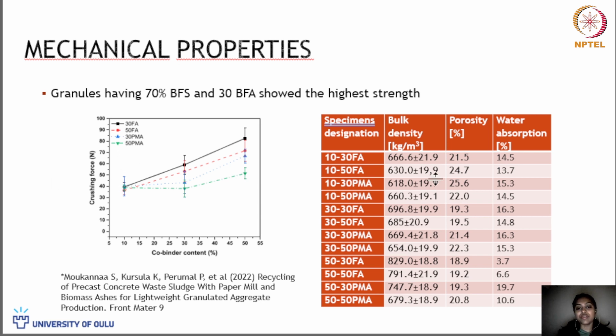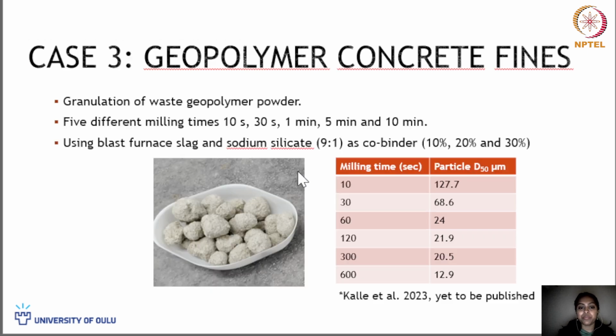So you see that the crushing force went up to 80 newtons, which is well above the crushing strength of the available lightweight aggregate granule, which we also tested. It is around 50 newtons normally. So that is one of the case studies.